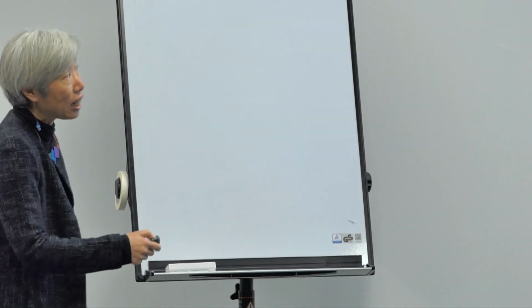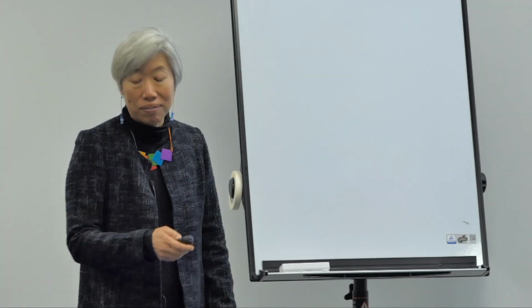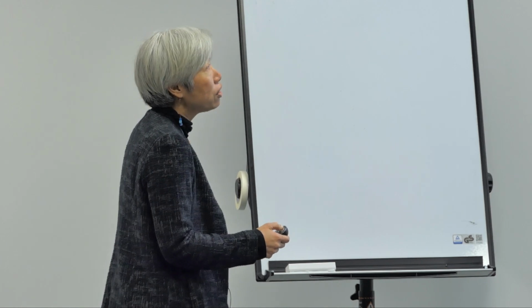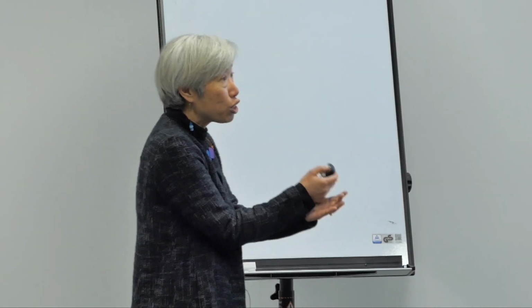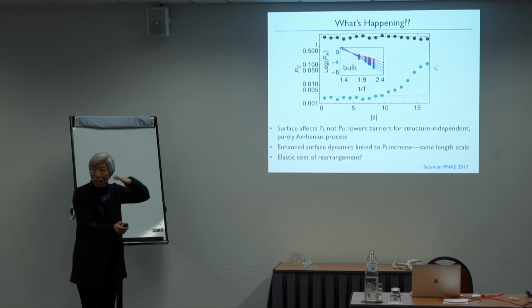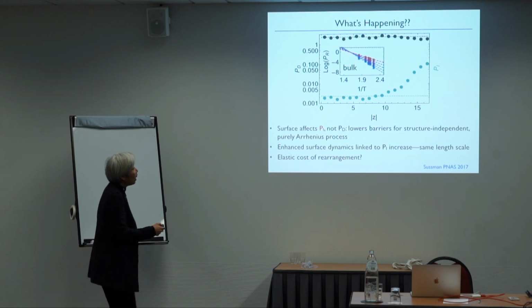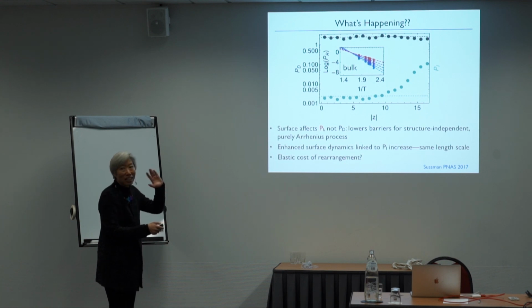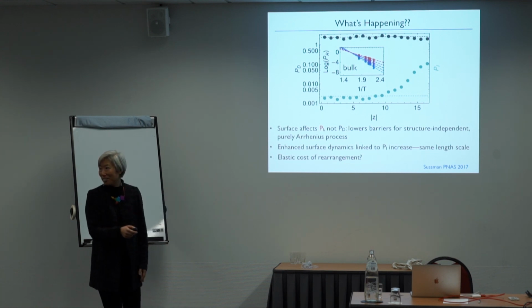And so that's saying the dynamics are changing without the structure. Okay? And so then we can do the same thing. We can look at the structure-independent piece, pull out the Arrhenius thing. And what you see is that the structure-dependent piece is totally flat. But the structure-independent piece, that is what is changing. And it's changing on the same length scale as the dynamics.